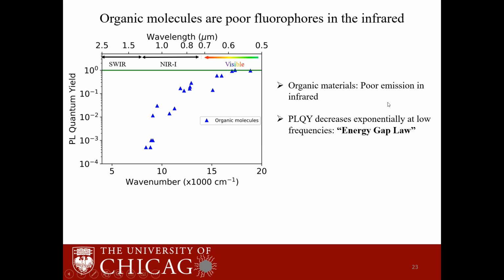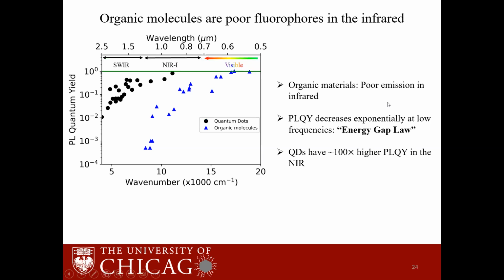This decreasing trend is called the energy gap law. The energy gap law arises because as we go to longer wavelengths, the energy of the organic molecule emission becomes closer to the vibrational frequency of the molecules, and this leads to a very fast non-radiative relaxation. But on the same plot, if we put the quantum yields of quantum dots, we can see that quantum dots are around 100 times brighter than these organic molecules. So even though quantum dots have a disadvantage of having a larger size and having issues of toxicity, in the shortwave infrared, there is no other material. But these are quantum dots that are solubilized in organic solvents. So for doing in vivo imaging, we want to solubilize these quantum dots in water.